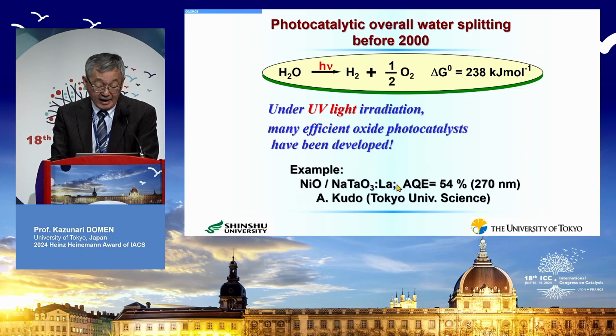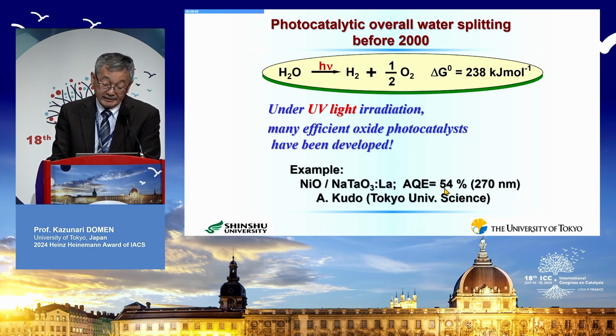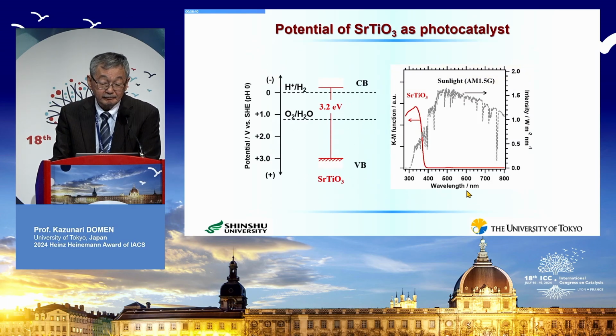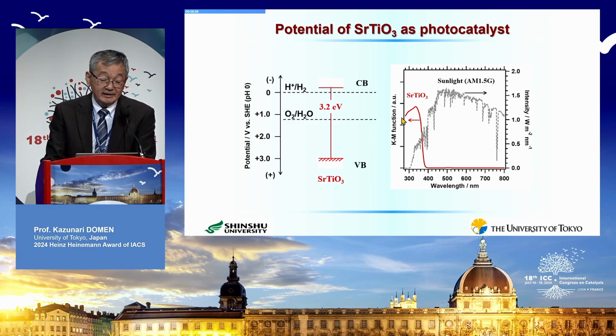Especially, I would like to emphasize the lanthanum-doped sodium tantalate modified by nickel oxide, which is a hydrogen evolution co-catalyst, and was developed by Professor Kudo at Tokyo University of Science. The apparent quantum yield was more than 50% at 270 nanometers. At this stage, this was the highest efficiency for the water splitting reaction. Now let me focus our attention on the strontium titanate photocatalyst.